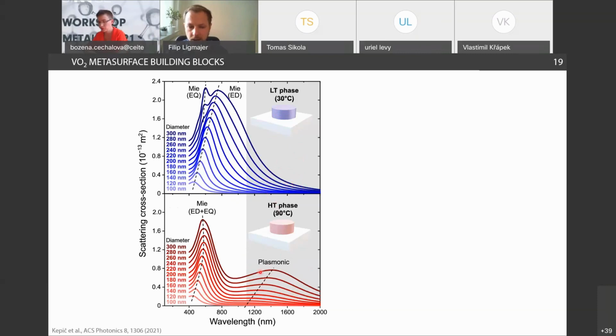Yeah, so the VO2 behaves like a metal here, and it exhibits plasmonic resonance at these frequencies, which is tunable as you tune the diameter of your disk. This is very well known and expected behavior. And at room temperature in the dielectric phase, there is no plasmonic resonance at all. However, as you go to short wavelengths, you observe different behavior.